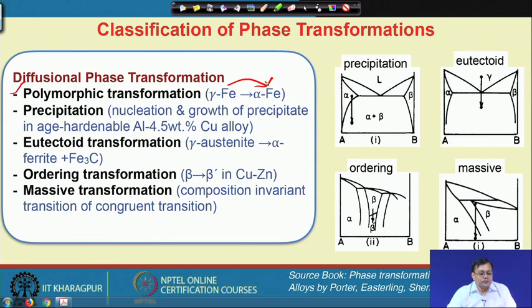Now, the second type of diffusional phase transformation is called a precipitation process. In precipitation also, it is controlled by nucleation and growth of the precipitate. As an example, I show you here an aluminum copper type of phase diagram. This is just a schematic diagram, and here A and B are two different components of the system, and they have a eutectic type of phase diagram, and they have a very low slope of this solvus line. This is a solvus curve.